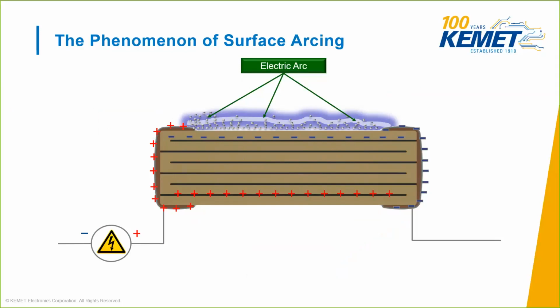When this occurs, a conductive path is created along the ceramic body, allowing the energy in the concentrated electric field of the termination area to discharge. The discharge of energy travels through the air along the surface of the capacitor. During the discharge, there is a visible and audible electric arc across the surface of the chip. It's important to note that some high-voltage ceramic capacitors can arc at applied voltages less than the rated voltage of the capacitor, and we'll see how to get around this issue in the next few slides.